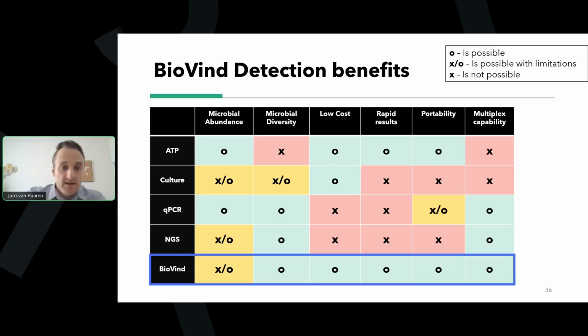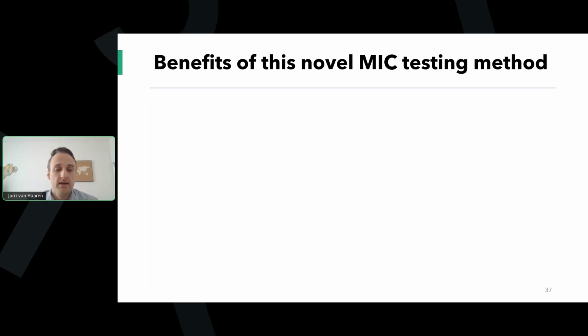We found that BioVind is really the only test that can tell you about the microbes in your sample without sacrificing cost and speed of results. Having a test that can tell you what's in your sample and provide details about what's actually going on in your pipelines or in your storage tanks or wherever you're doing testing, and do that quickly, same day, easily, and at a low cost, is super powerful.